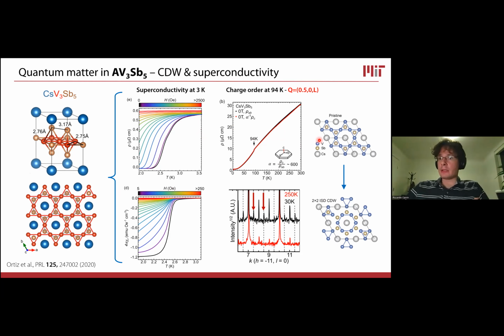And so what happens at the symmetry breaking transition that gives us charge order? Well, what happens is that the pristine unit cell doubles in both planar directions. So you go from a pristine unit cell, which has just the ABC sublattice of the Kagome network that I told you about before, to a 2x2 enlarged unit cell, which can have different patterns, and that's still a matter of active debate. The example that you see here is the one called inverse Star of David, which essentially means that these hexagons shrink a little bit in the middle, and these triangles shrink also. And this gives you this overall distortion that you see pictured here. And so the characteristic wave vector, because it's a 2x2 distortion, is (1/2, 0). So this is a period 2 charge order.